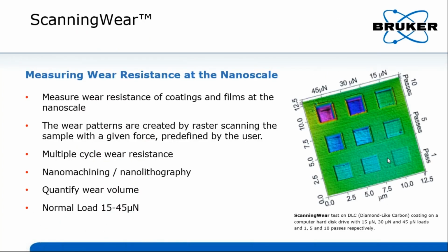Let's go back to take a look at the scanning wear in detail. Based on the in situ scanning probe microscope, SPM, nanowear can be done by setting the scanning load at different levels. In addition, the number of passes is also a useful parameter for nanowear. After finishing nanowear with the set force and number of passes, the post image can be collected using the in situ SPM to quantify the wear volume. It is not only for nanomachining shown in the previous case, but also powerful to measure wear resistance directly.